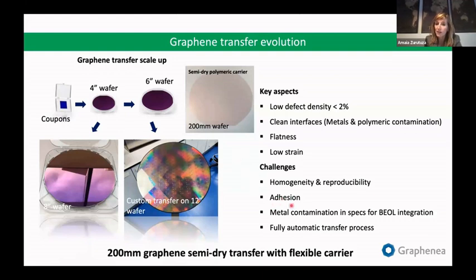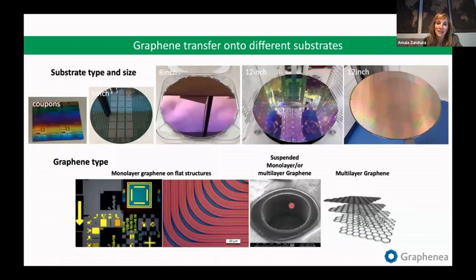So the graphene on these substrates is just touching. They are held by van der Waals interactions, so these interactions are quite weak. What can happen is that graphene can detach from the substrate. So you need to optimize the transfer process in order to improve this adhesion and maintain the full film on the substrate. I will show you an image of what happens when you have bad adhesion. Basically, it's not good, but I think it's the next slide after this.